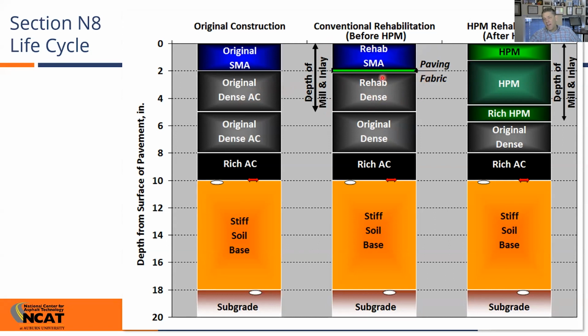This made it about 3.5 million ESALs before we had a lot of surface distress, and trucks were having to veer around this test section. It started to impact some of the adjacent sections. And that's when I think it was Nam Tran and Buzz and a few others had this idea of, well, we've gotten what we can out of N8. Now we have to hopefully make it last for the next 7.5 million ESALs to get to the end of the test cycle. Well, let's try putting in this high polymer material on top of an extensively cracked and damaged pavement, and let's see how it performs. We had a lot of confidence coming out of what we were seeing in the adjacent section N7. Let's try it here and see what happens.